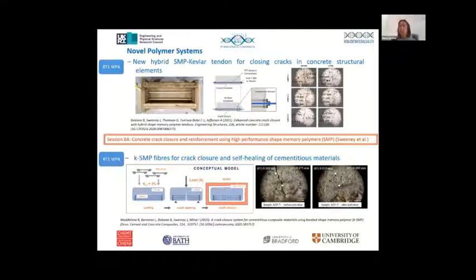And obviously when these tendons are placed within a concrete beam or a mortar beam, that then results in a compressive force applied to the structural element, which we can use to close any cracks that occur perpendicular to the tendon. And we found that we can generate sufficient pre-stress, when we have a certain area of tendon, to close our serviceability limit state cracks, which is absolutely fantastic news. And we're developing the next form of these now to look at different activation techniques and also anchorage of the tendons, working quite closely with Bradford again on that. And again, I know there's perhaps a talk on that on Wednesday afternoon.